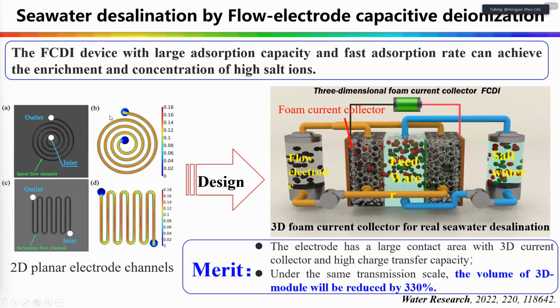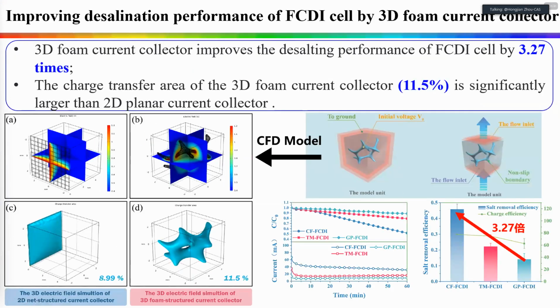After finishing that part, we call it the 2D planar electrode channel. We think it's not enough, so we developed the 3-dimensional foam current collector. This collector shows more enhancement for the FCDI desalination performance. We can find this. We get a 3.27 times improvement. And also the charge transfer area is larger than the 2D planar.